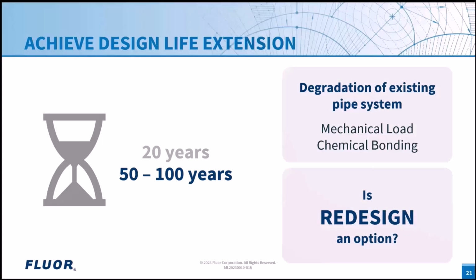This large extrapolation from 20 to 50 years still introduces some uncertainty. For the mechanical loads applies that if during the 20 years of exposure they have not crossed the 50 years threshold, it could be decided that 50 years would also have been okay. On the other side, various end users and also vendors have applied short-term tests on excavated pipes that were exposed to 20 years of design loads, or sometimes even longer. In general, these tests show no degradation of the mechanical properties. So what we see is that developments are going on, and we might expect in one of the following revisions of the standards a section that addresses lifetime extension.